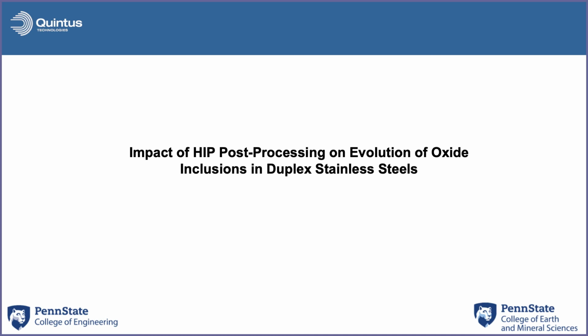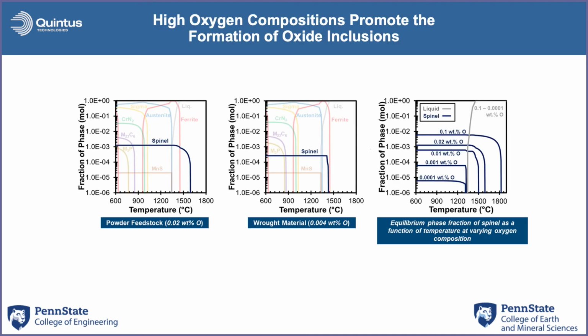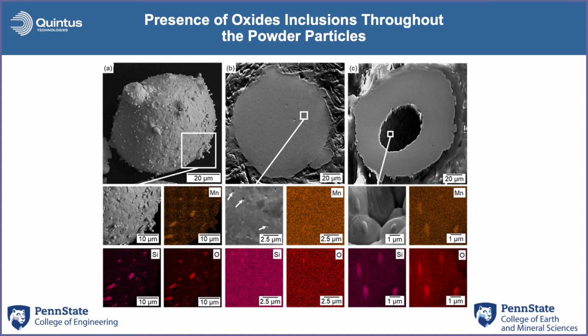Another area that we're really interested in is the role of oxide inclusions. Since most of the time in additive we start with a powder, we can have upwards of an order of magnitude more oxygen in an as-built AM part than we would in a wrought component. Once again, that shifts the thermodynamics. So whether you're talking CALPHAD, whether you're talking ICME, whichever the appropriate buzzwords are for this week on the use of computations, it allows us to start looking at how they evolve.